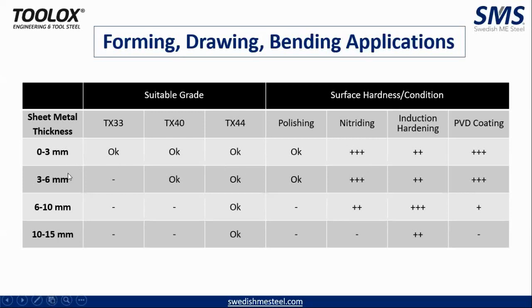If your sheet thickness increases from 6 mm to say 10 mm or 10 mm to 15 mm, then those are a bit complex applications for the material per se. So it requires higher hardness as well as a higher surface treatment. There we recommend Toolox 44 plus induction hardened, so that you have both high hardness at 55 to 57 HRC, and also the thickness of the induction hardened layer is 2 to 4 mm.